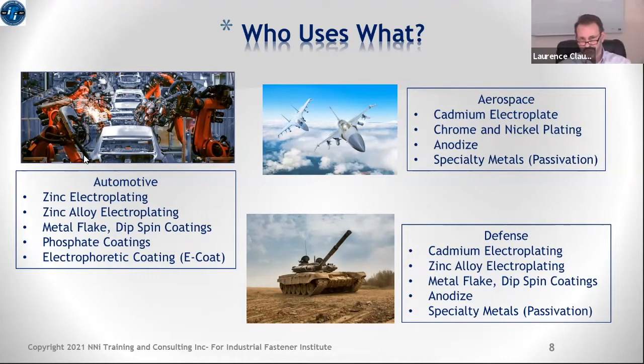So you can see in automotive, the primary coatings and platings are a couple of the zinc electroplatings, both the zinc and the zinc alloy electroplatings, the metal flake platings, phosphate coatings, and electrophoretic coatings, which is electrically applied paint, otherwise known as E-coat. In aerospace, you can see cadmium electroplate is a very common one, chrome nickel, anodizing of aluminum, and again, the use of specialty metals, protections of specialty metals like stainless steels and the nickel alloys. In a very similar vein, the defense industry uses many of those same general categories. Again, you see cadmium plating, and again, the specialty metals.